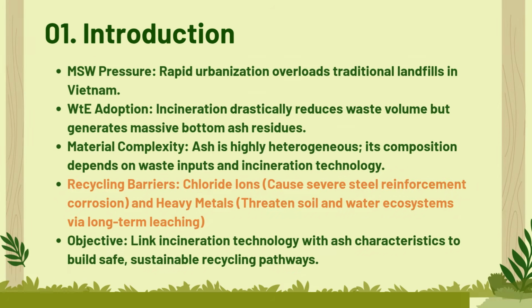Vietnam is facing increasing municipal solid waste due to rapid urbanization, making waste-to-energy incineration an effective solution for reducing waste volume. However, this process also generates a large amount of bottom ash. The main challenge is that bottom ash contains high levels of chloride ions and heavy metals. Chloride ions can cause steel reinforcement corrosion, while heavy metals may contaminate soil and water through long-term leaching.